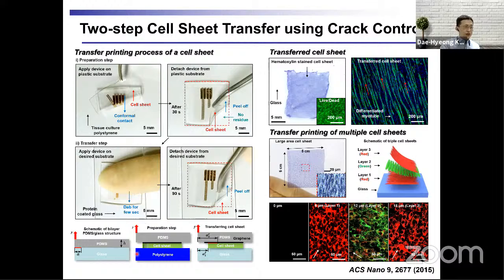After culturing the cell sheet, now we need to transfer print. Our transfer printing process doesn't require temperature change. Rather, we need a two-step procedure, a preparation step and a transfer step. What we need to do is just contact the cell sheet to a temporary plastic substrate and detach it. That's it. If we make a conformal contact of the cell sheet to a polystyrene substrate, for example, and detach it, then a crack will be generated at the edge of the cell sheet. Then this cell sheet is ready for transfer printing.